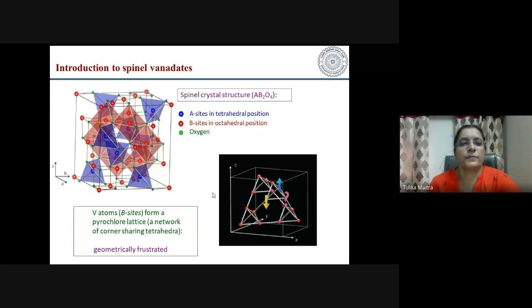So one can have this on a non-geometrically frustrated lattice. Coming to this class of compounds, which are known as spinel vanadates, or spinels in general. The spinel crystal structure has the chemical formula AB2O4, where the A site is tetrahedrally coordinated by oxygen, shown here, and the B site is octahedrally coordinated by oxygen, and the B sites further form a pyrochlore lattice, which is a network of corner-sharing tetrahedra, as shown here. So this tetrahedron is also geometrically frustrated.